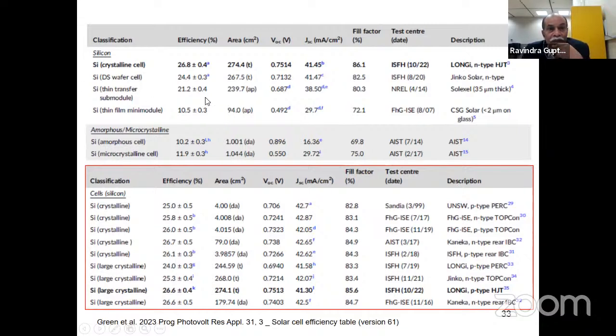But for the thin film, this is 21.2. But when we have a mini module, thin film, this is 10.5%. This is from company CSG Solar. Here, the thickness is less than 2 micron. Okay, the thickness is very, very thin. What about the amorphous silicon? You can see this is very, very low, 10%, 11%. And this is for a small area. And when we increase the area, it will be further less.